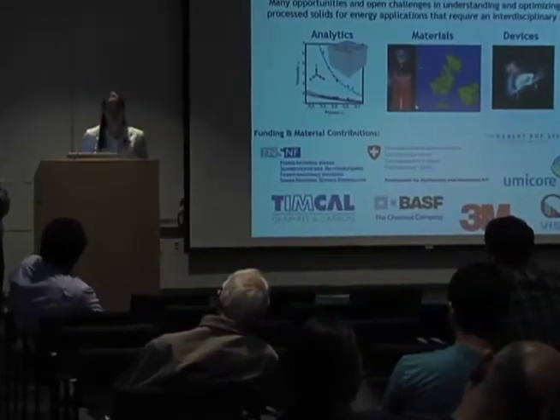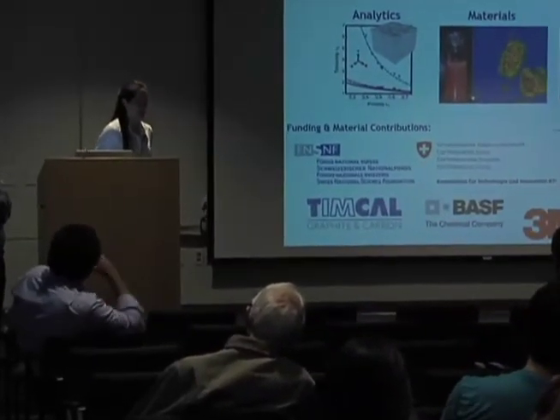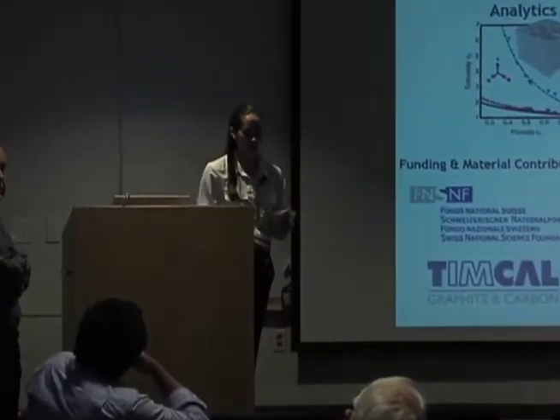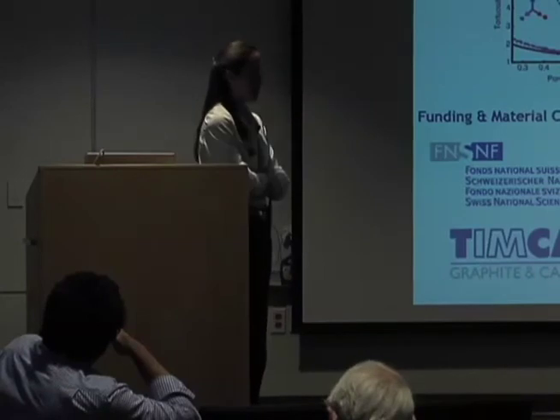Well, that's one thing that's very different depending on how you treat the surface of your quantum dot. Certainly in a lot of cadmium selenide systems where you have either very long insulating ligands or thick shells, people have reported more hopping-like transport. But in these lead sulfide-based systems, people have also been reporting band-like transport.